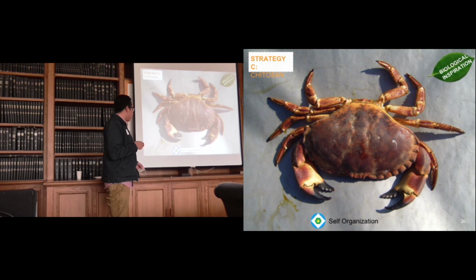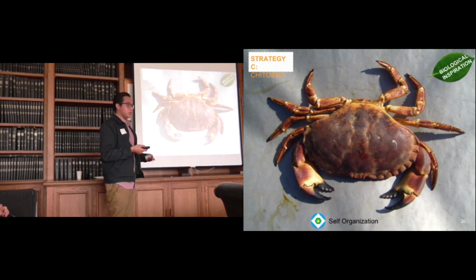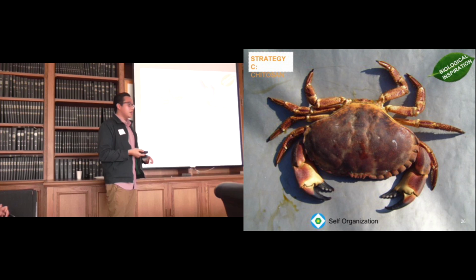In terms of the bio-inspired approach, we really looked at self-organization because chitin does organize itself to provide the first layer of protection for arthropods. So the shell protects it from anything really penetrating inside its body. And before I move on to the next slide, I also want to point out that in terms of sourcing of chitin, you can actually break down the shells of arthropods, remove the calcium, and then you can use a sodium hydroxide solvent to deacetylate the chitin into chitosan. You can also buy this from chemical manufacturers like Sigma Aldrich.